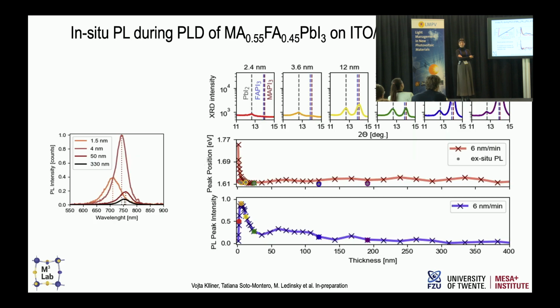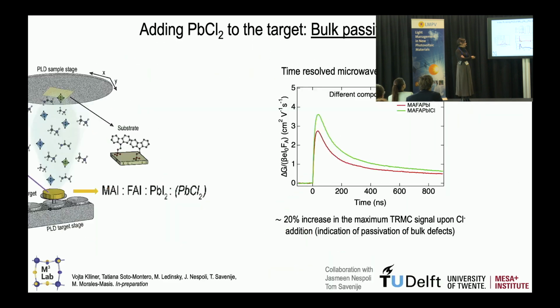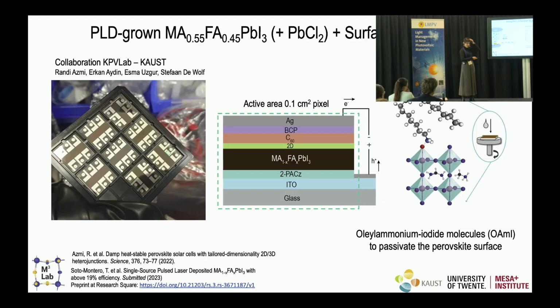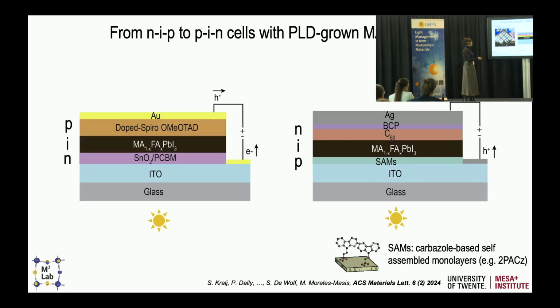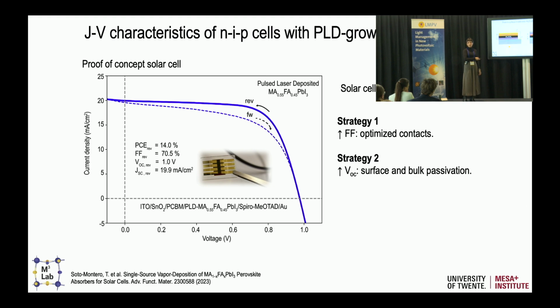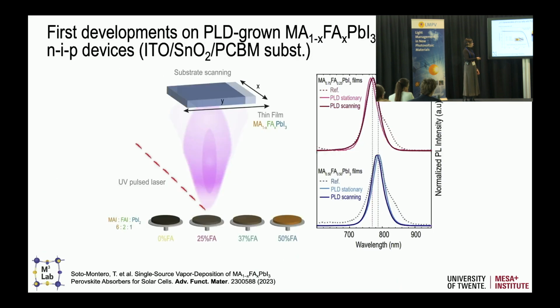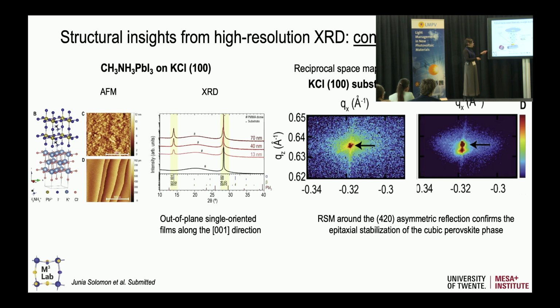Yes, yes, they are. I think I will have to go back a lot. But yeah, we are working on it. Jonia is working on that, right? Yeah, our goal is to have a single crystal. That's absolutely the case. You see, the small grain is the nuclei. There are nuclei, but they are all oriented in the same way. But if you continue growing, it will be, as you said, columnar. We did actually do mobility measurements as well, and we see that it is limited by the grain size. So if we manage to have grains without these grain boundaries that coalesce into a single crystal, that will be great.